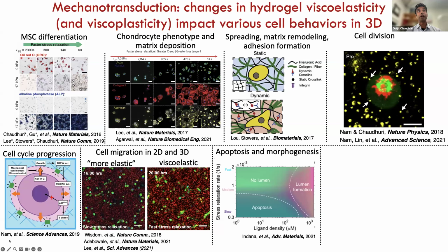Similarly, when we culture chondrocytes or cartilage cells in these hydrogels, we see that again in the fast-relaxing hydrogels, the cells are able to secrete a lot more type 2 collagen and aggrecan, here in yellow, a much wider volume of interconnected cartilage-like matrix, essentially. From these two areas that we've studied, we can appreciate how viscoelasticity might be a potent design parameter for biomaterials we use in regenerative medicine. We also see an impact of viscoelasticity on cell spreading and adhesions, matrix remodeling, mitosis, cell cycle progression, as well as cell migration, apoptosis, and morphogenesis.